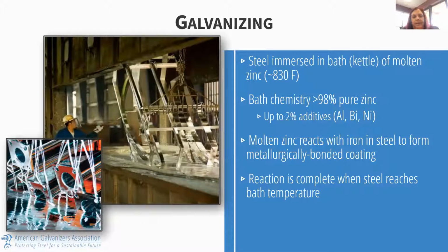A little bit about the galvanizing bath. It's heated to about 830 degrees Fahrenheit. It's required to be at least 98% pure zinc. The 2% of additives, there are limits within this, but it is to the galvanizer's discretion. The most common that you'll see are aluminum, bismuth, and nickel. These help with things like the fluidity of the zinc, the shine of the coating, and controlling the coating thickness.